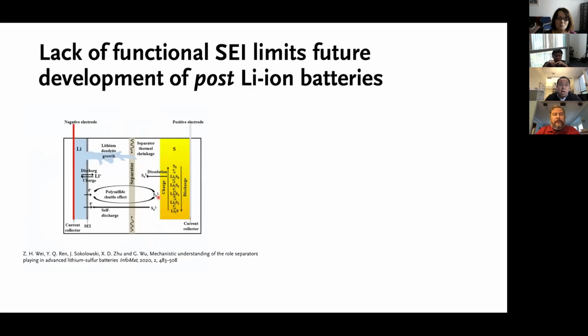Well, if you don't have this layer, what happens is that when lithium deposits, it has a tendency to do what's called the dendrite growth. And this is one of the intrinsic properties of lithium. Many factors contribute to it. For instance, at the tip, you probably have a very high electric field. So that's why lithium prefers to deposit here.